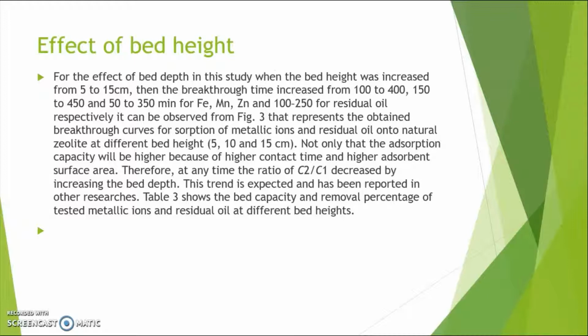So for the effect of bed height, we can see that when we increase the bed height from 5 to 15 centimeter, the breakthrough time increased from 100 to 400, 150 to 450, and 50 to 350 minutes for ferrum, manganese, zinc, and 100 to 250 for residual oil, respectively.